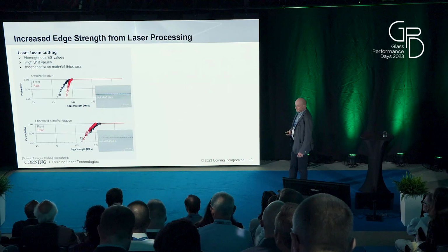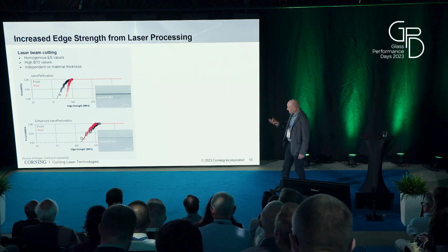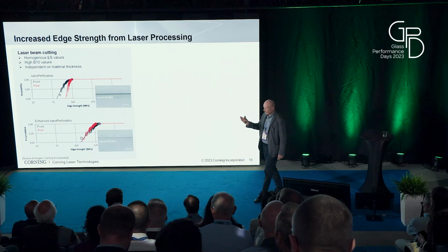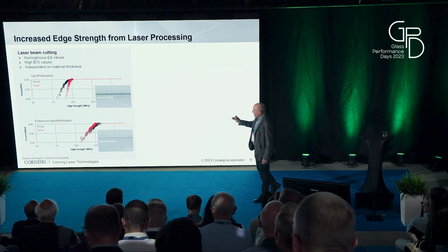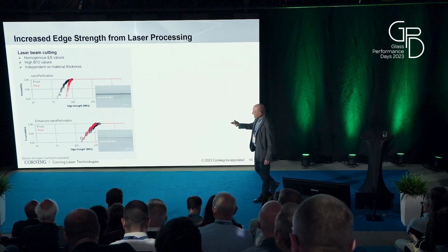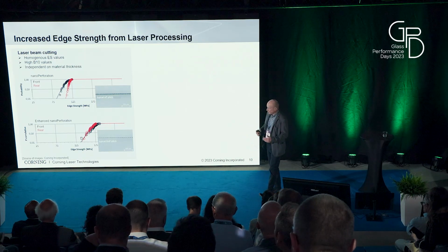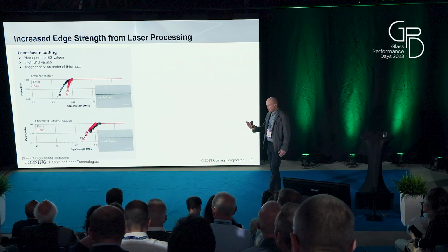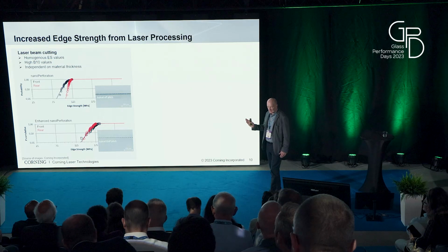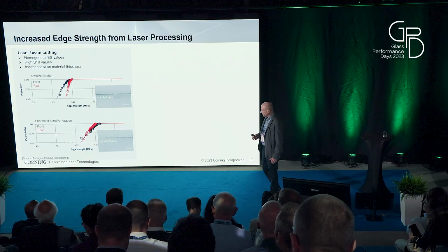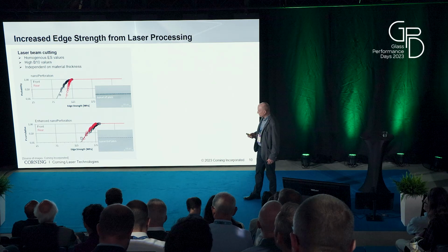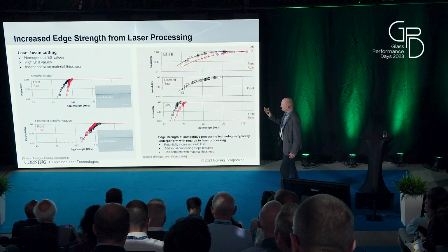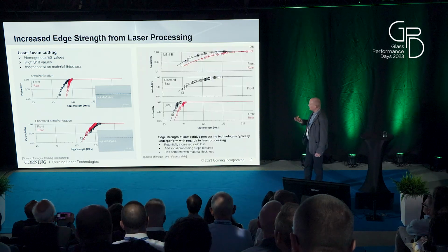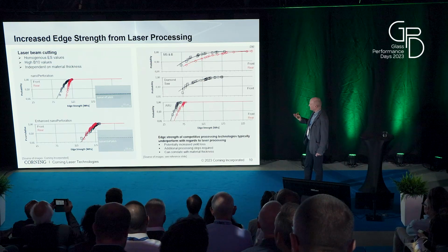First of all, we have a fairly high edge strength, typically between 80 and 100 megapascals. And with our enhanced nanoperforation, that's an improved version, essentially we push that by an additional 30 up to 50%. So we can land typically at 150 megapascals with our enhanced nanoperforation. Compared to that, of course, the results with mechanical cone break and other methods are not as good.